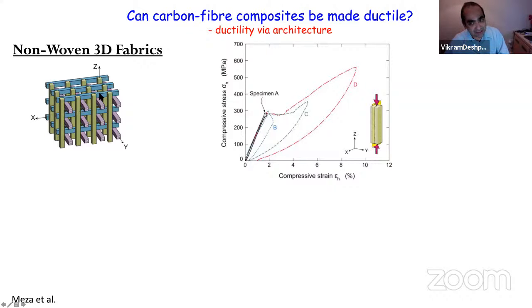And we do a compression test in that Z direction. We are effectively compressing these Z direction tows because the other tows are doing very little. And we're plotting the compressive stress against the compressive strain. These are 4 different experiments, and we load and we unload. Look at what strains we have reached for this specimen D, and we could have gone on much more: we have reached compressive strains of 10% or so, and there is no sign of catastrophic failure.